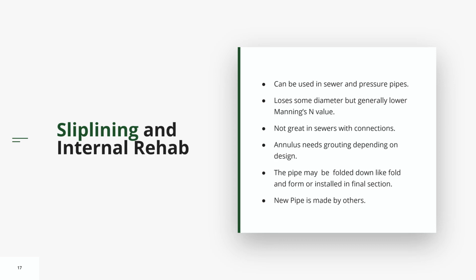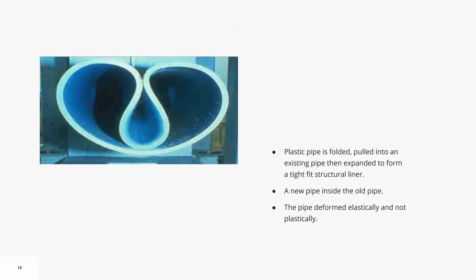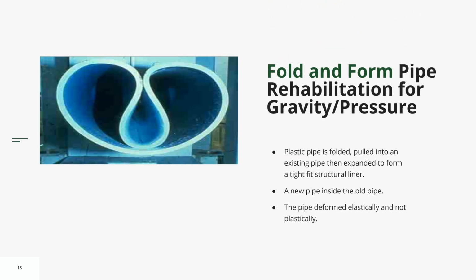Here we're looking at a fold and form. So what we're doing is we're taking a plastic pipe here. It's not your typical plastic. It's a slightly different formulation, but it's deformed elastically. You don't take it to its plastic limits, obviously, even at those extreme bends of that U that's in the middle there. That still is not a plastic deformation. It's still elastic, and when you pop this back up, it will form a brand new pipe.